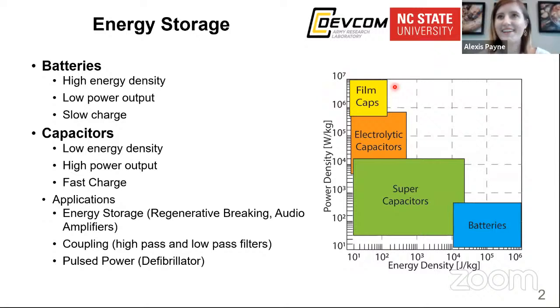Yeah, great question. The surface area we don't have to calculate, it's a spec on the spec sheet that you get when you order the foams, since they're so commercially available. But in terms of our electrical characterization, we know what the polarization should be per unit area on a planar surface. So we can calculate how much surface area is actually contributing to our polarization when we measure it on the metal foam, and do a direct calculation to show how much surface enhancement has gone into the nickel foam versus planar. Also, we haven't explored it, but you can buy nickel foams at a variety of porosities, so that is something we can explore in the future. It's denser or wider or bigger just by ordering different types.